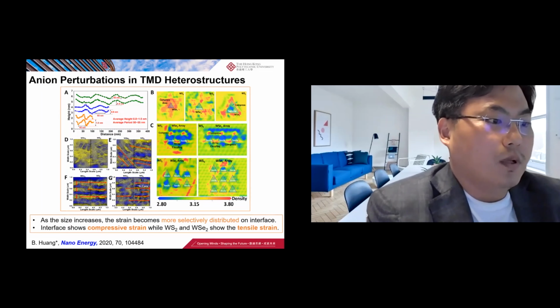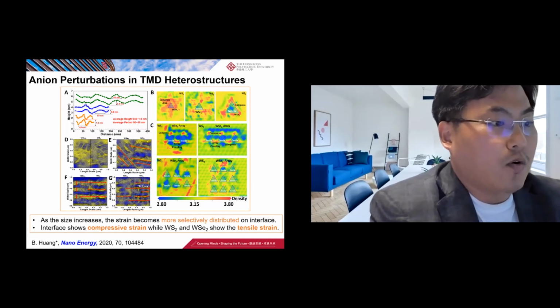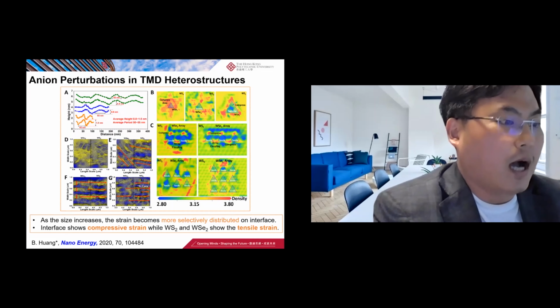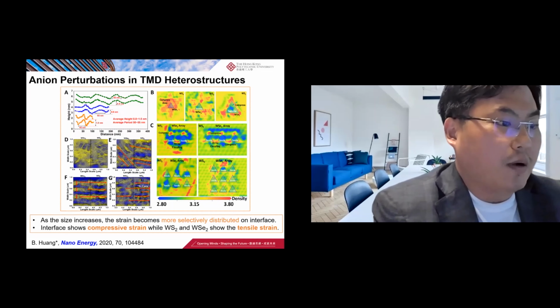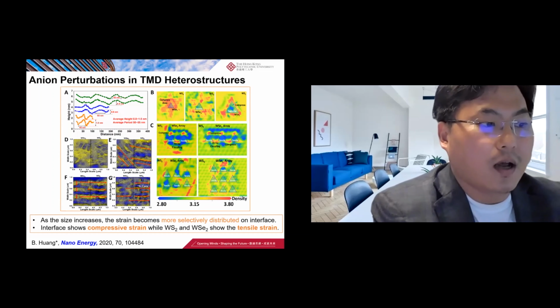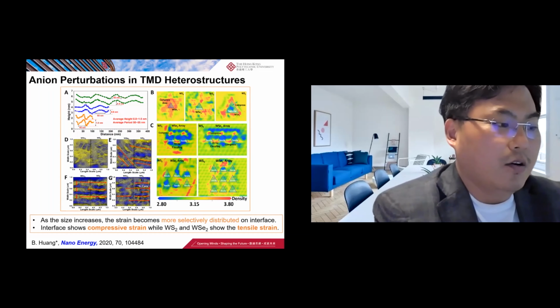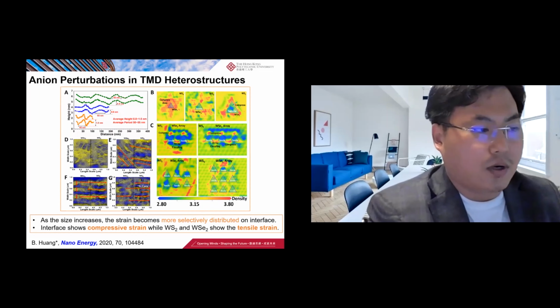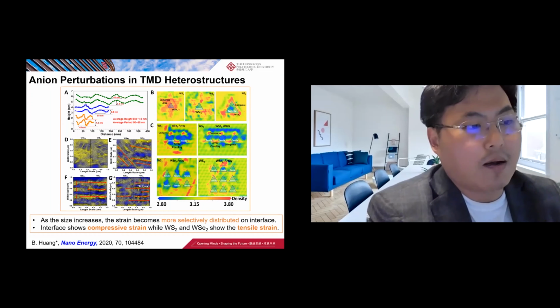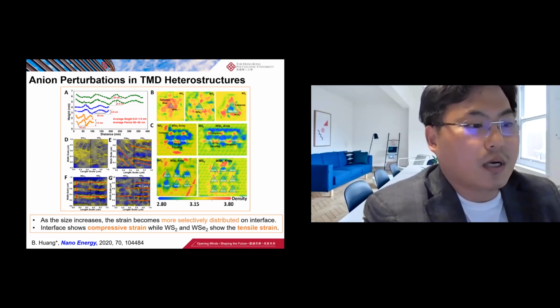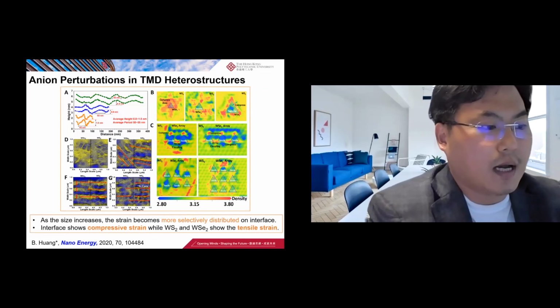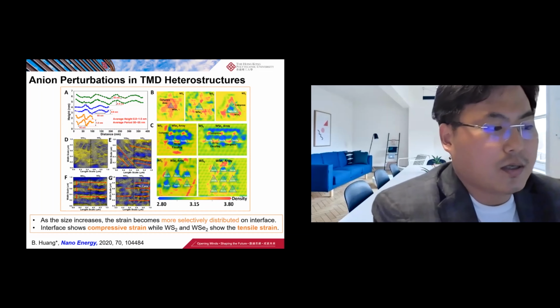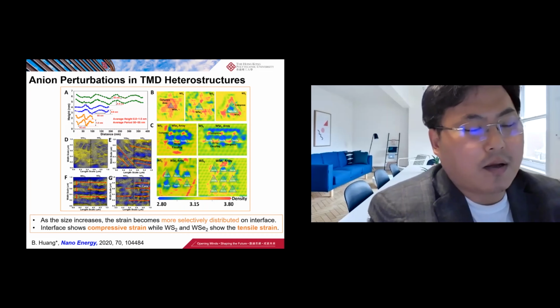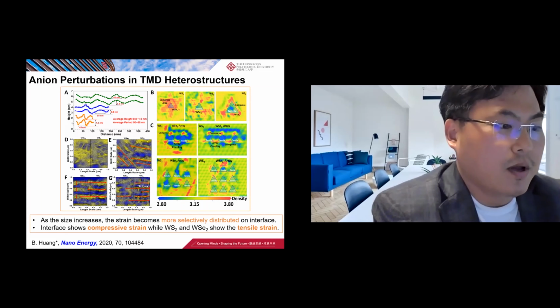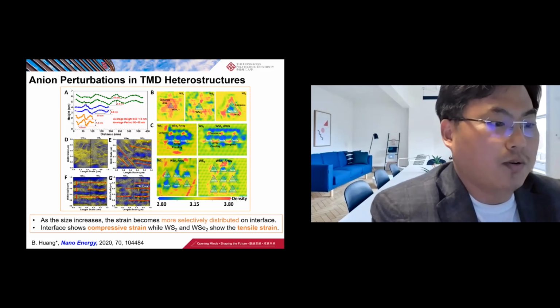And we have achieved progress in exploring the two-dimensional heterostructures from the atomic levels. So then, what we see from this slide is that we have further enlarged the theoretical models to a larger size, from several tens of angstroms to several tens of nanometers, or even trying to approach the micrometer scales. So we have constructed arrays of the heterostructures corresponding to the experimental observations in atomic force and microscopic scales. Similarly, the ripple structures can still be noticed at the interface.